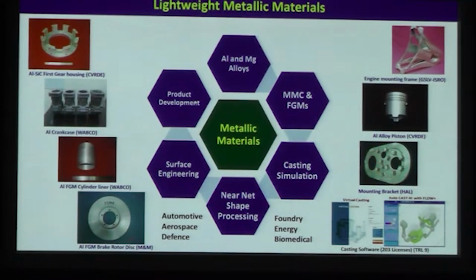And low pressure casting is mainly used to make components with porosity-free castings, because normally in gravity casting or sand casting there is a lot of leaking. But when we use low pressure casting, the casting problems can be solved and we can get a better, premium quality casting. This is an engine mounting bracket which was developed for HAL.